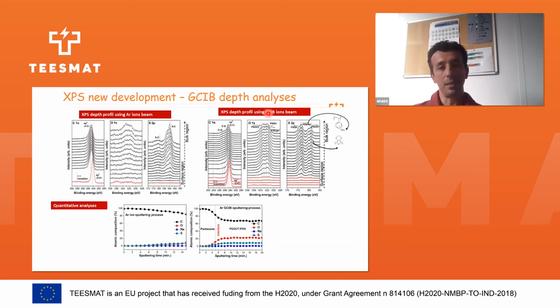Let's start with GCIB. With GCIB, when we sputter, we have two signatures of PEDOT and PSS. When we look at the sulfur peak, we have two peaks. And when we etch, in fact, we etch a few minutes and we record XPS spectra. And we can see that the signature of PEDOT:PSS remains stable. We do not have any change in the chemical structure.